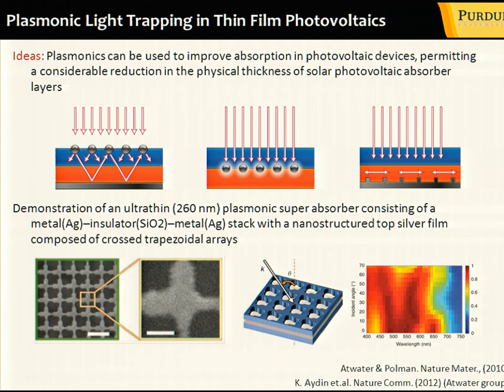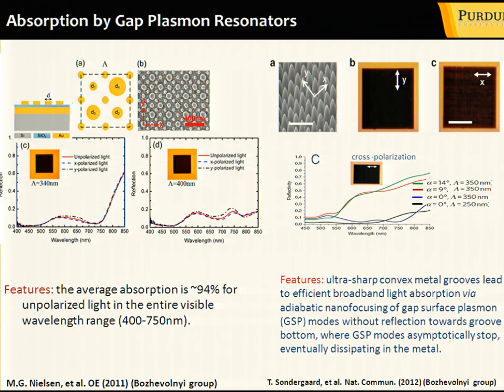Here you could see work done by Harry Atwater. By the way, recently Harry Atwater and Albert Polman got the Energy Prize, which is a very prestigious prize, for their work related to using these nanophotonic elements to improve photovoltaics. In this case, they use these trapezoidally shaped structures, which are basically metal insulator metal waveguides with silver being the metal and the insulator being just silica. And they showed very strong extinction for a very broad range of angle of incidence and in a broad spectral range. And of course, the hope here is to replace silica with photovoltaically active elements such as silicon.